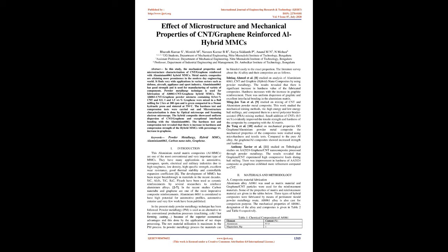microscope. The hybrid composite showcased uniform dispersion of CNT/Graphene and exceptional interfacial bonding with the Aluminium 6061. The hardness test and compression test revealed that there is an increase in hardness and compression strength of the hybrid MMCs with percentage weight increase in Graphene. Keywords: powder metallurgy, hybrid MMCs, Aluminium 6061, carbon nanotube, Graphene.